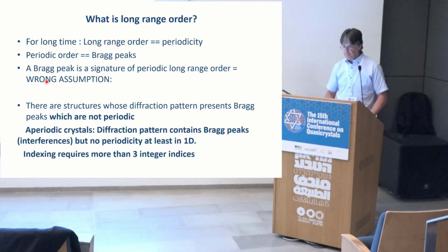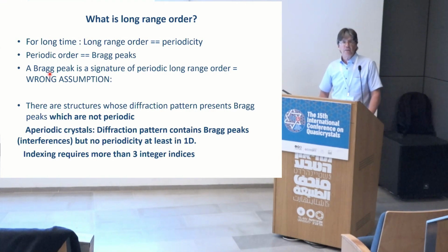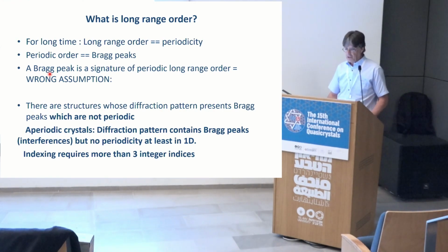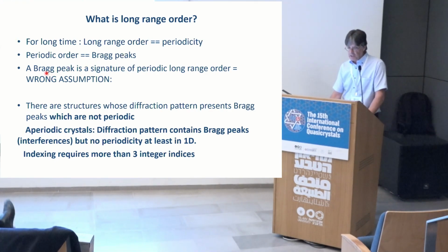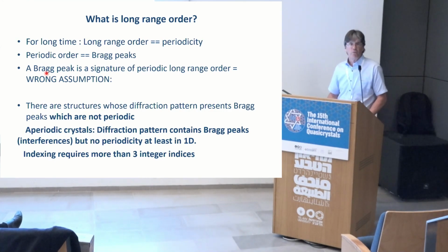aperiodic crystals really raised the question, what is long-range order? So for a long time, long-range order, and that's what I've just introduced to you, was associated with periodicity. Periodicity was synonymous with long-range order. And because we have periodic order, we have Bragg peaks. That's the way we see it in an experiment. And the assumption that was made, which was completely wrong, was that a Bragg peak is a signature of periodic long-range order.